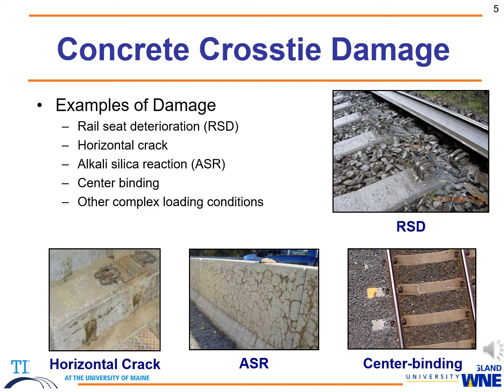Here are some of the most common concrete cross tie damage types found in the field. One is rail seat deterioration. This is when the bottom surface of the rail rubs on the top of the concrete cross tie, creating a deteriorated surface, which in turn tips the rail. Another is horizontal cracking due to the pre-stressed wires inside of the concrete cross tie. Another one is ASR reaction. Another is the structural failure of center binding, and also many of the other unpredictable complex loadings that create moments and shear stresses that can't necessarily all be considered in design.